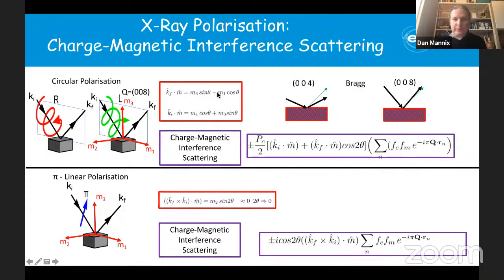And that in principle as well will change your contrast to domains. So the different domains will have different contrast just because you've got these different factors. If this was a magnetic moment direction, the projection onto these moment directions is different for the different Bragg angles. The second thing to say is that if you have a small angle scattering regime, you can do kind of imaging.